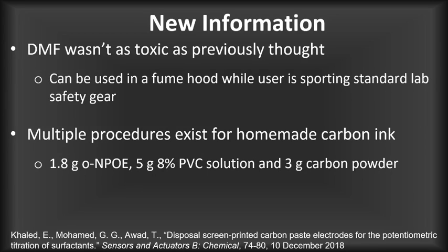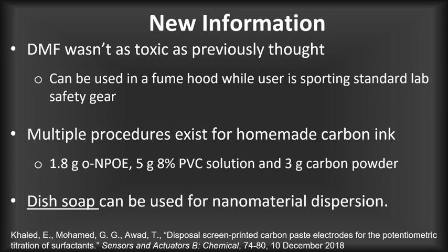Also, I found out that I was not the first one to attempt do-it-yourself homemade carbon ink. And I found a pretty good recipe in an article that requires 1.8 grams of ONPOE, 5 grams of 8% PVC solution, the same PVC that's in PVC pipes, and 3 grams of carbon powder. And I also found something interesting. One of the things that we wanted to do was to modify our screen-printed carbon electrodes, and to do that, we needed to have nanomaterials dispersed in a medium. Dimethylformamide was that medium, but I also found that dish soap can be used for nanomaterial dispersion. And I found that kind of interesting because of the whole DIY theme that we were going for, and so I decided to carry forward with that.